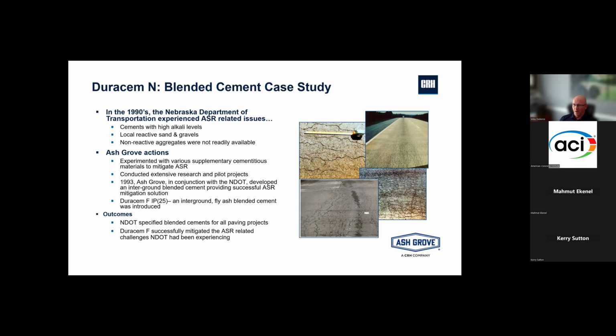They did not have a locally feasible non-reactive aggregate to help combat that. So Ash Grove, operating the cement plant there in that region, worked with the Nebraska Department of Transportation to come up with a solution. We experimented with various SCMs to help mitigate ASR through extensive research and pilot projects, working hand in hand with NDOT. Then in 1993, we introduced a product known as our Duracem F. It's an IP(25), an interground fly ash and cement product. It's done a fantastic job of mitigating the issues that they were having in that market.